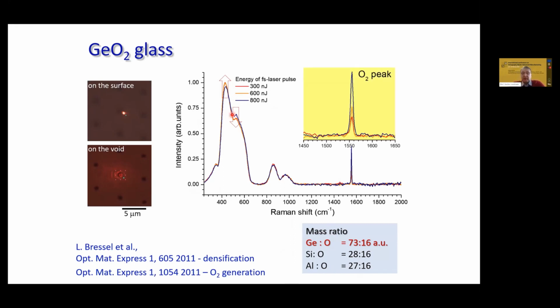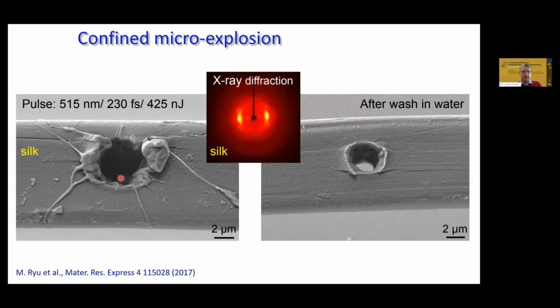But if you look for the place where you expect oxygen, you see that you can detect oxygen, and depending on how much energy was in your femtosecond writing pulse, you will see different concentrations. So oxygen is actually inside the void, which you create with the femtosecond pulse. So it was hard materials, oxides, but the same logic is valid for crystals, for example, biocrystals.